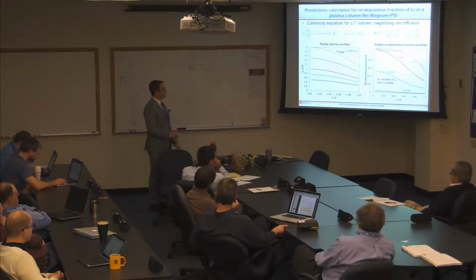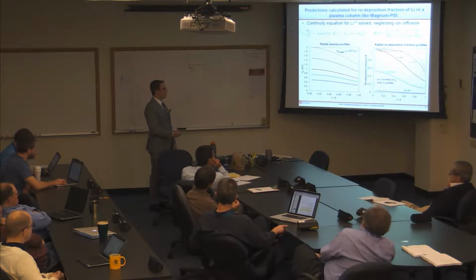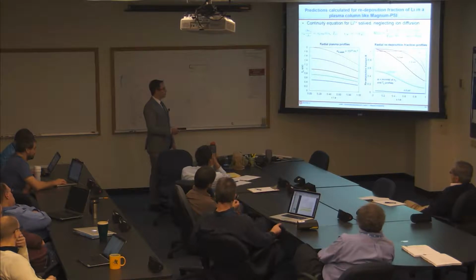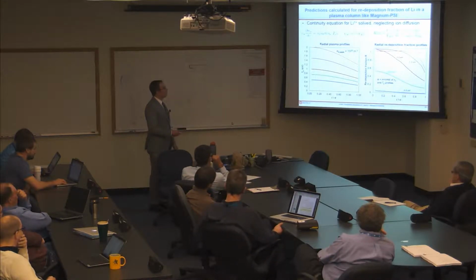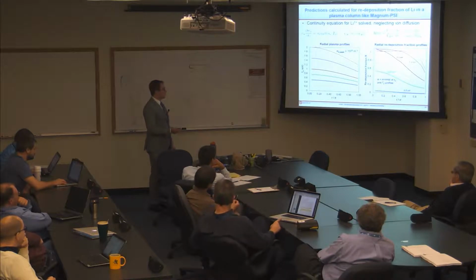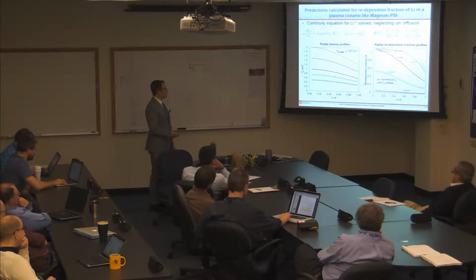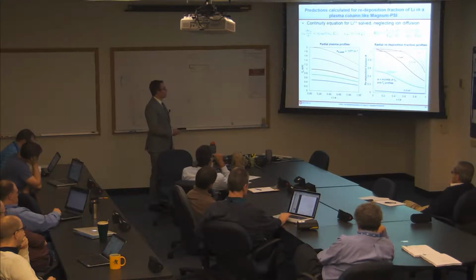So this is the formula for the redeposition fraction. As I said, it's the flux of ions back to the surface divided by the flux of neutrals from the surface. And if you just want to do some simple approximations for what the redeposition fraction should be, I just made some very simple Gaussian temperature and density profiles. So this is R over sigma, where sigma is the half-width at half-max, so it's an independent measure, independent of the specific spatial dimension. Both the density and the temperature measurements looked like this. And then you infer what the redeposition fraction should be.